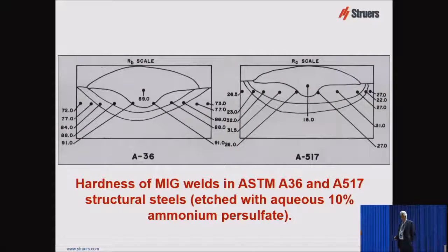And here's examples of the hardness on these samples. On the left, we're using the Rockwell B scale, and on the right, the Rockwell C scale. And these slides were made before we're now calling them officially HRB and HRC in the ASTM literature. But these pictures are fairly old. And you can see the hardness value going 72 here in the base metal, 89 in the weld metal here. And you can see right here it's 77, and then 84, and 88, and 91. So there's an increase in hardness as we're going across.